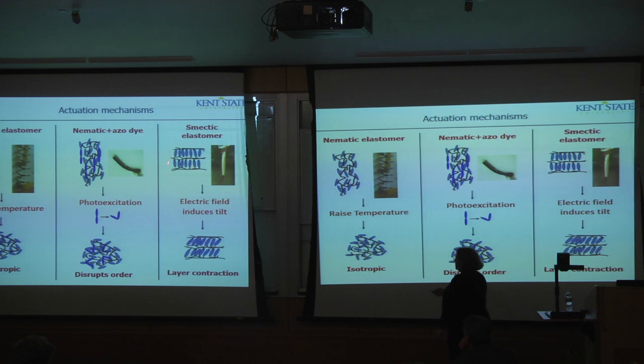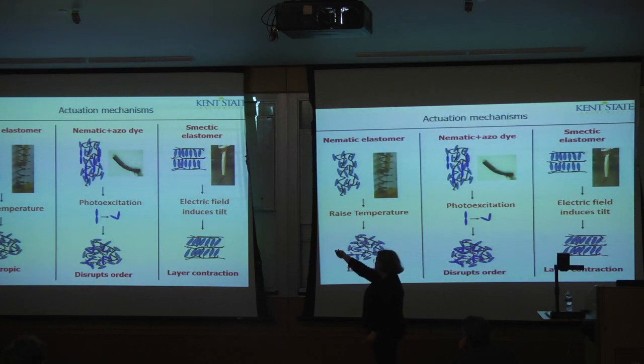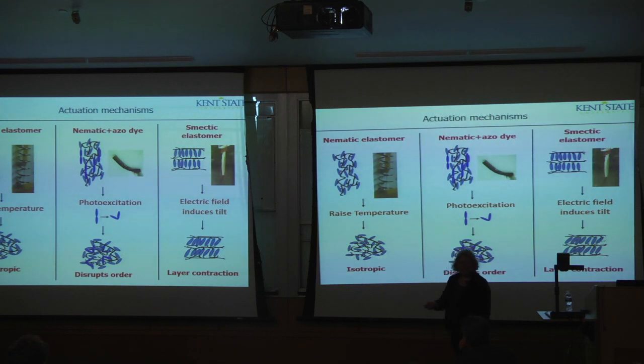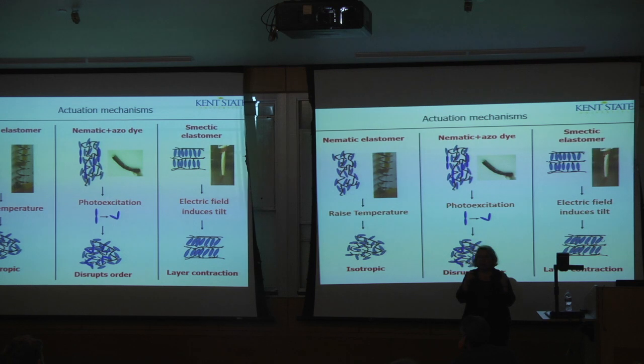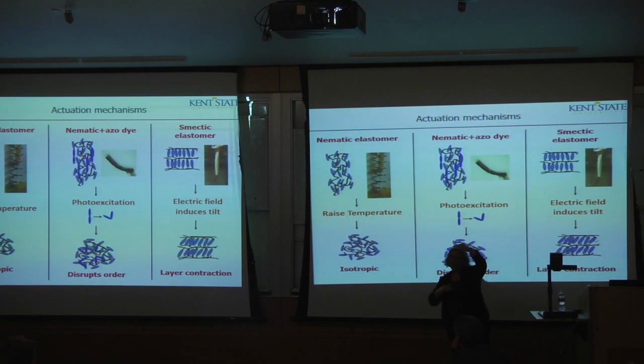Okay, and then in the third case, we have a smectic elastomer that has layers. Here it's shown in the smectic A phase, where the molecules are aligned parallel to the layer normal. When you apply an electric field this way into the board, that induces a tilt. Think what happens when you have books on a shelf and they tilt: their spacing this way gets smaller. So we expected that the electric field would just make the whole thing shrink, but instead it twisted.